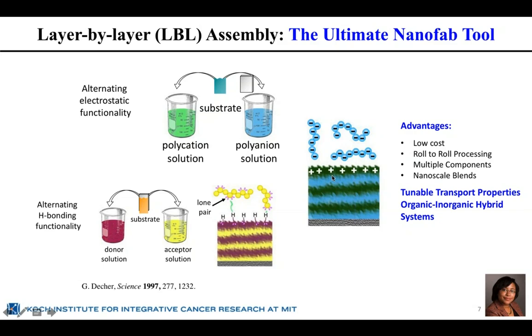Now, these layers can be as thin as essentially the molecular cross-section of a polymer chain, just a few angstroms, to as thick as several tens of nanometers, depending on the ionic strength and pH of the solution and the charge state of the system that is being adsorbed. So we have a great deal of room for tuning these materials. The polymers themselves, although we're making these independent layers with each step, are really polyplexes in which there's a great deal of interpenetration from one chain to the next. So you can imagine that a polymer chain that is adsorbed in layer number 4, for example, may actually have chain segments that go down as deep as layer 1 or as high as layer 8, depending on the type of system that you incorporate.